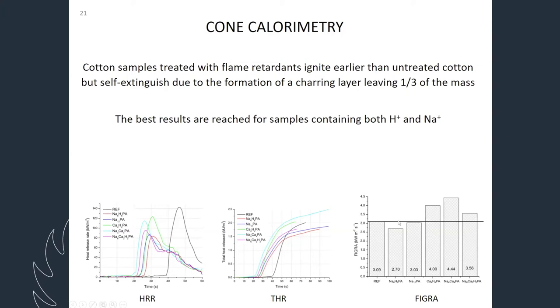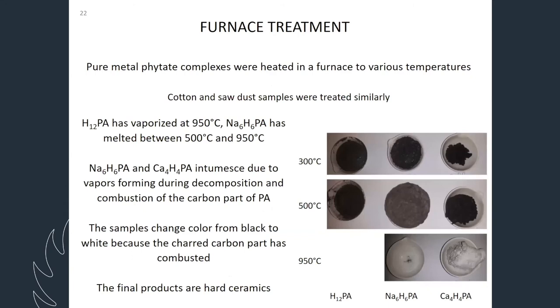Here we can see only the sodium salts, they are actually better. The lower the figure, the better is the fire retardant behavior. So the sodium salt with proton is the best in this respect. We also treated our samples in the furnace.